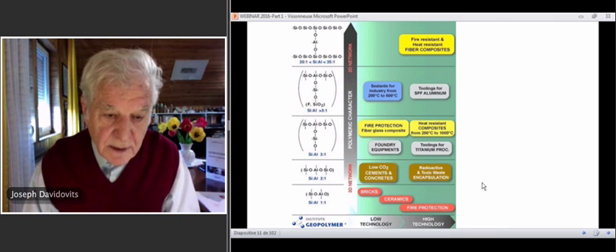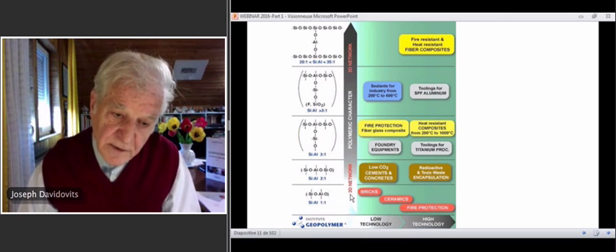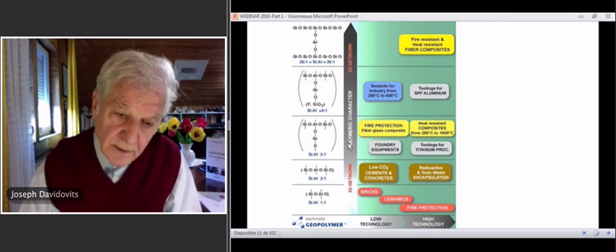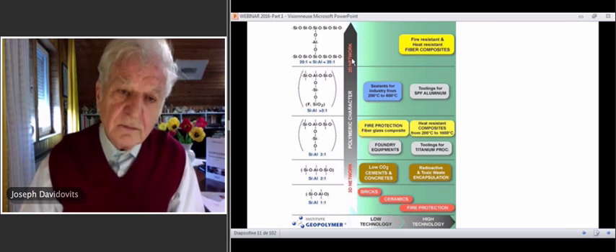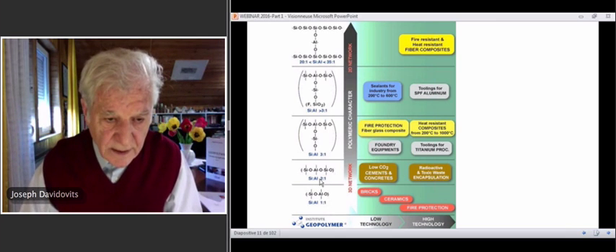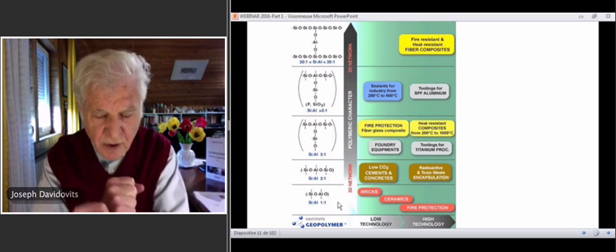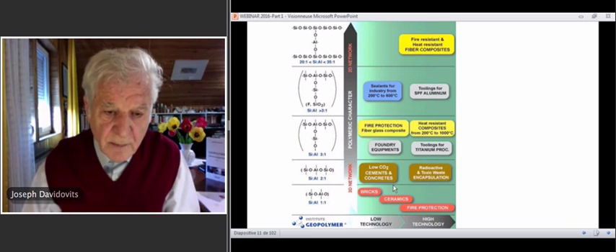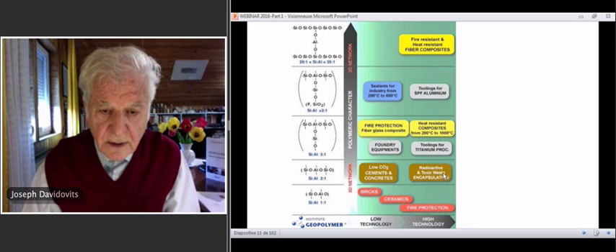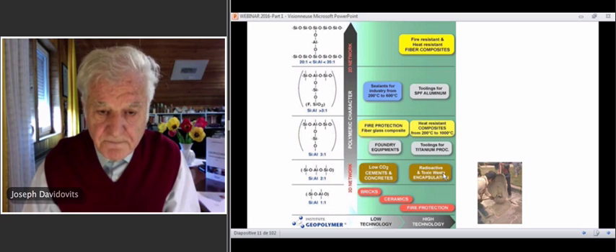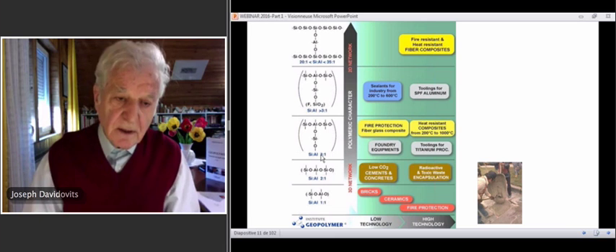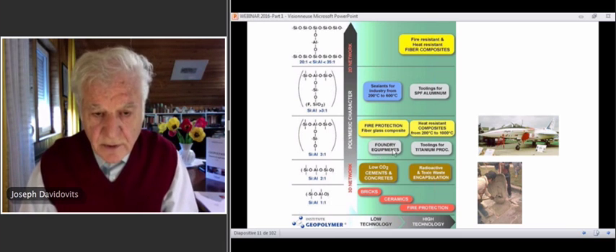If we look at the applications, they strongly depend on the chemical makeup, on the Si:Al ratio. We have here a three-dimensional network. This is the polymeric character of the molecules, and it ends up in a more flexible material. Si:Al 1 or Si:Al 2 are three-dimensionally very strong networks, and they are used either for bricks or ceramics, for cement, low CO2 cement and concrete, and radioactive waste encapsulation. And then if we increase the silicon amount in the molecules, Si:Al ratio 3 to 1, then we enter into very special uses in terms of making tooling prototypes at high temperature for the industry.